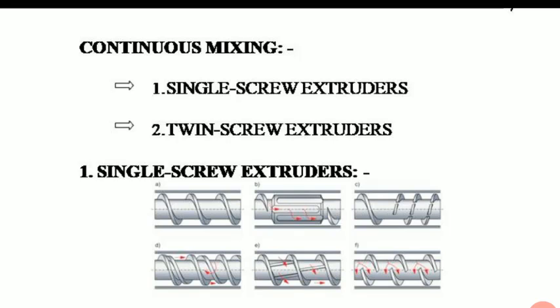Normally, the mixing process in a single screw extruder is laminar, and the material being mixed exists as separate layers, and the process of mixing involves reduction in the striation thickness. However, at the end of the process, the components of the mixture still exist as discrete components. The total shear strain exerted on the melt is a function of the residence time of the melt in the process.